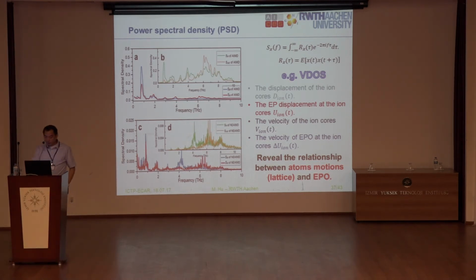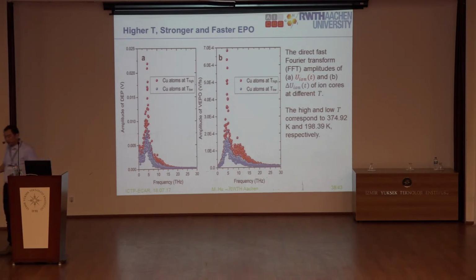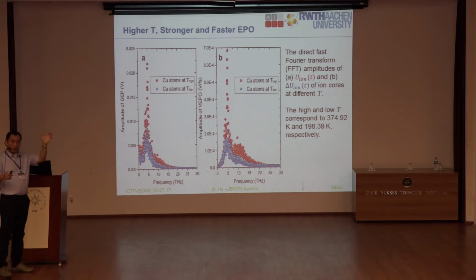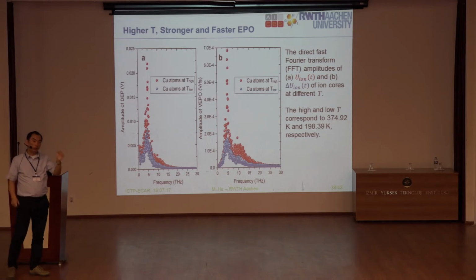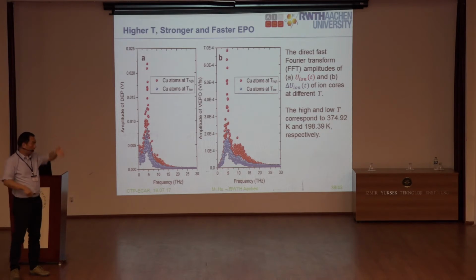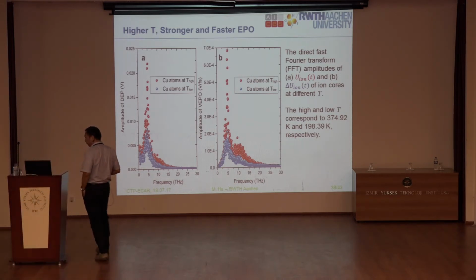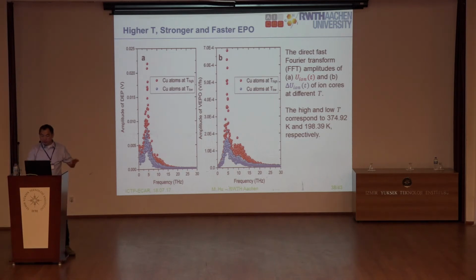And after that, we also found that if you have different temperature regions, a high temperature and a low temperature, then you have different electrostatic potential oscillations. It means that once some region has a high temperature, the vibration of the lattice is very fast and severe, and then you have higher amplitudes of this EPO, and at the same time the vibration frequency is also very fast. So this gives us the foundation of this concept.